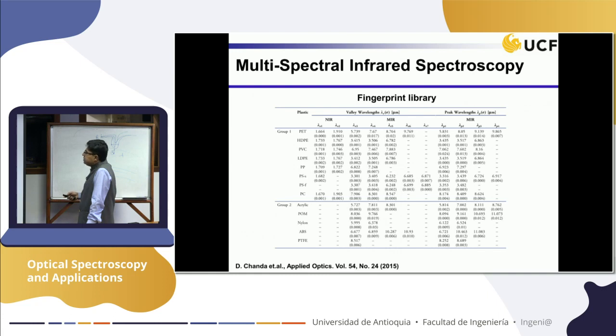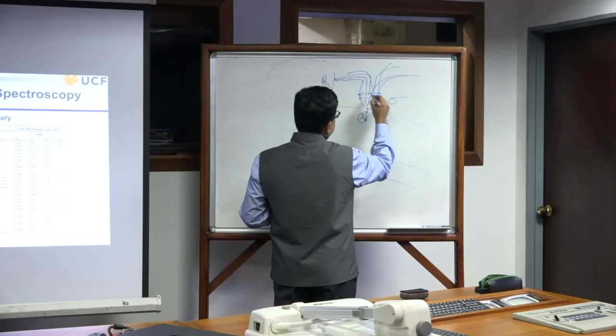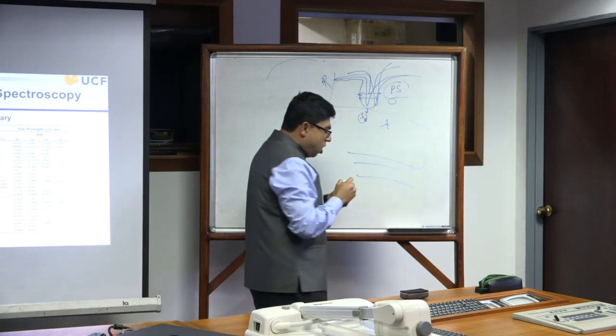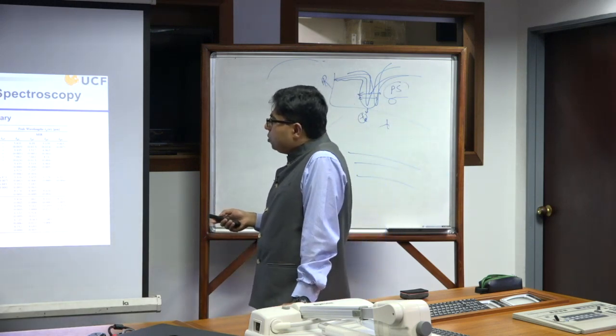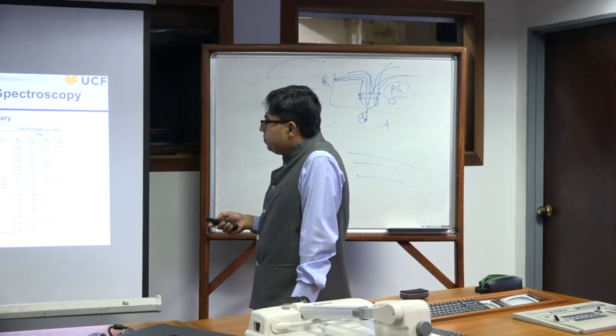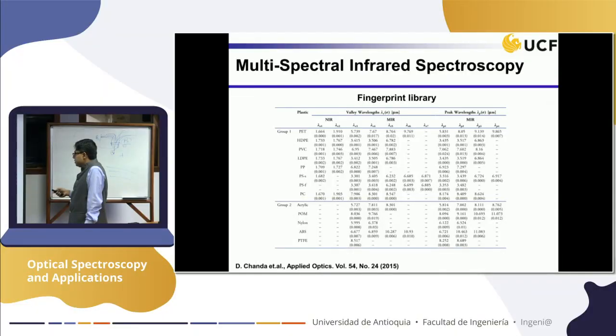Over say 50 samples, we saw that a spectral location has a 0.001 micron variation. So you capture their distribution, the statistical variation, also in the library, so that when you measure a plastic and you see a response somewhere here, and you know this is within your sigma, within the standard deviation, you know this is maybe a polystyrene. So for all the spectral locations, we capture not only the location but also their variation across various samples. You need to measure many samples to create a fingerprint database. And as I was mentioning, we capture both the valley and the peak.